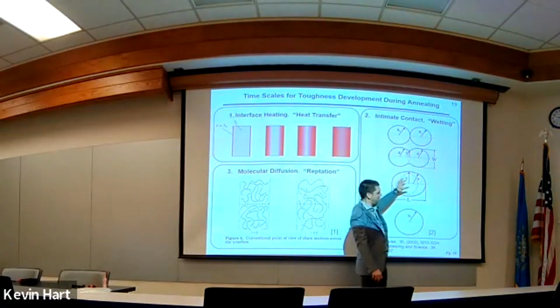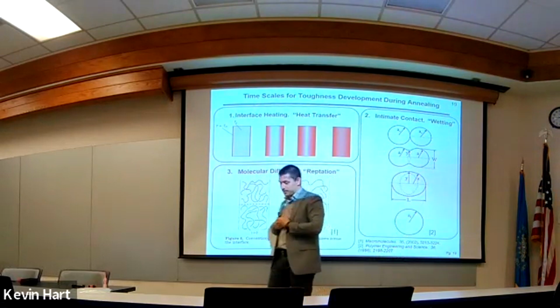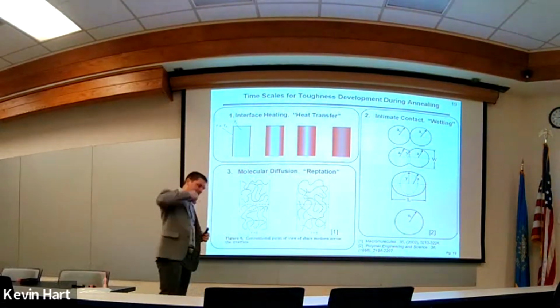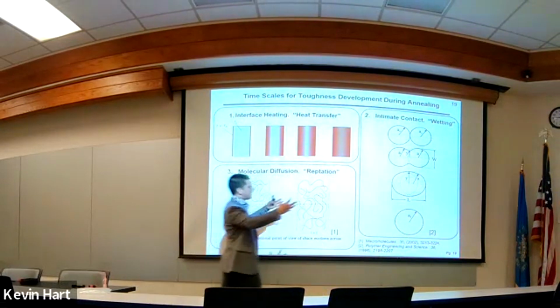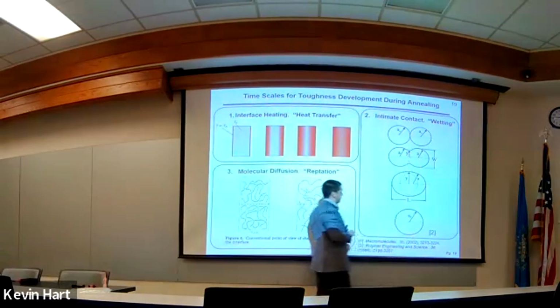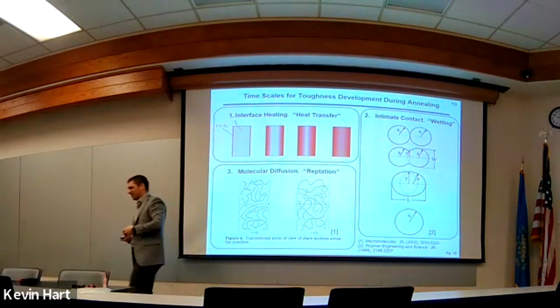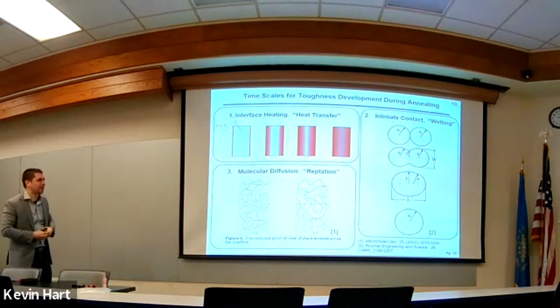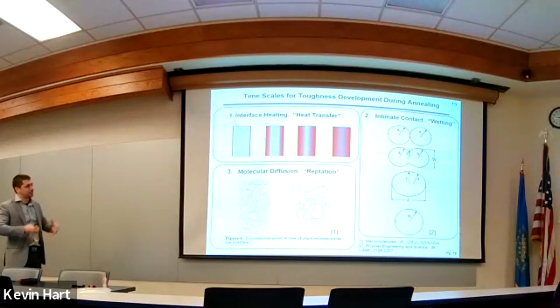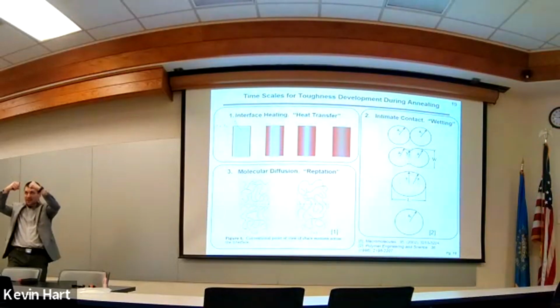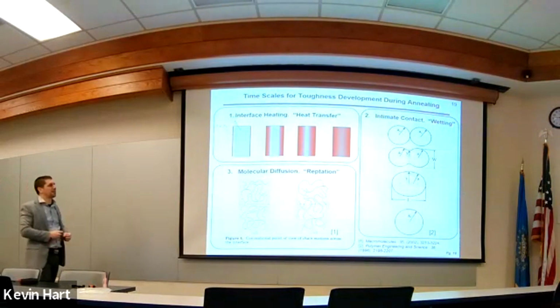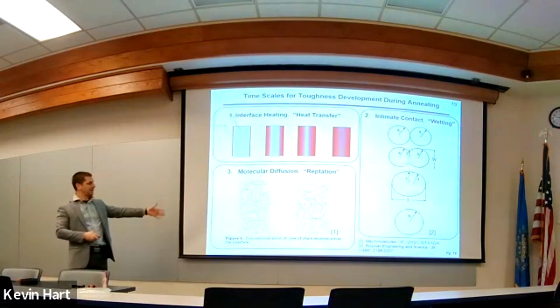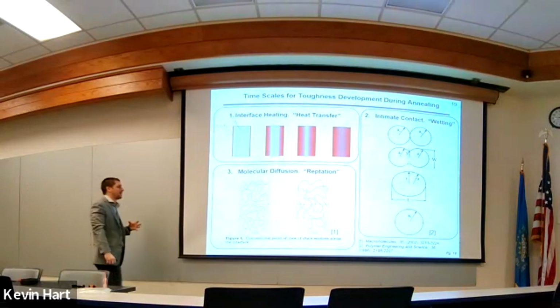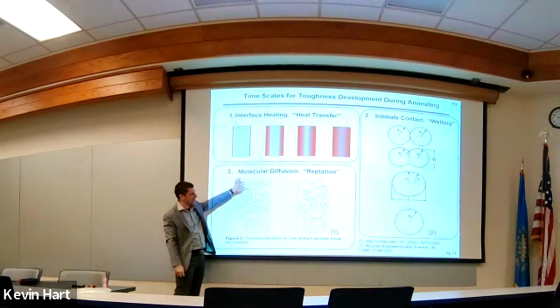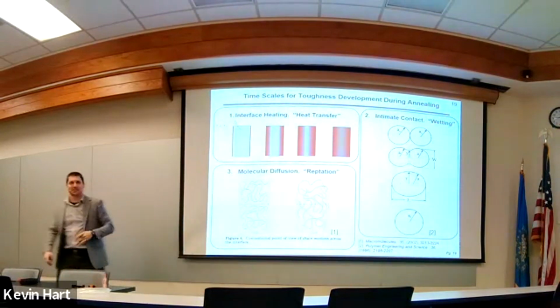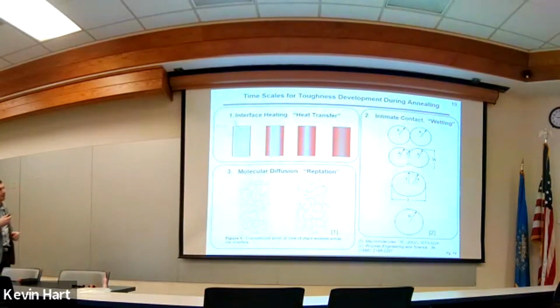There's also some physics that have to happen between the 3D printed roads that you print, right? So you've got these 3D printed lines that are next to each other and they actually have to migrate into each other. And there's this whole body of literature about this. It's called sintering. So there's a lot of polymer processes that rely on sintering as well, but this whole process of getting those two layers to meld into each other, it's called wetting. And so there's a whole body of literature associated with that, okay? Then lastly, once those things have made intimate contact and wetted with each other, this reptation has to happen, which is, again, back to our French scientist, Pierre de Gennes, talks about the timescales associated with reptation.